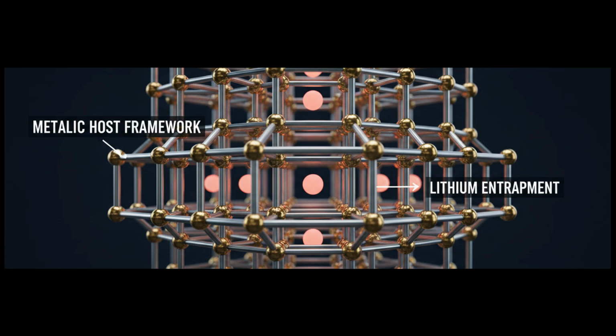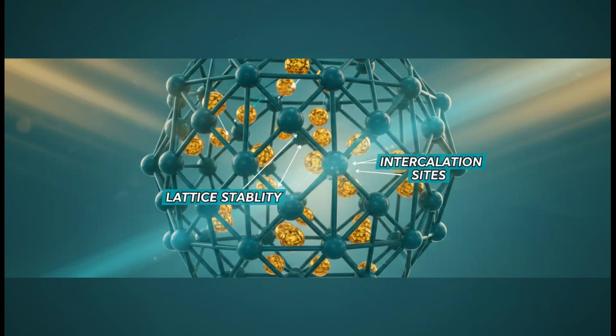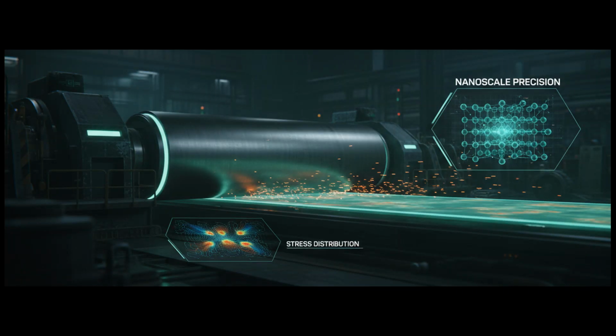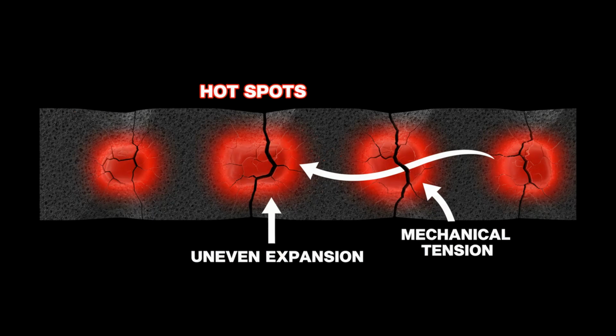The secret lies in the host material. Ganfeng uses a proprietary blend of metals that form a rigid, conductive framework. This framework acts as a cage for the lithium atoms. When the battery charges, the lithium ions don't just pile up on the surface. They migrate into these specific sites within the alloy lattice, filling the gaps without pushing the atoms apart. This is a feat of precision manufacturing. The alloy must be uniform across the entire surface of the anode, down to the nanometer scale, to ensure the stress is distributed perfectly. Traditional anodes crack because the expansion is uneven.